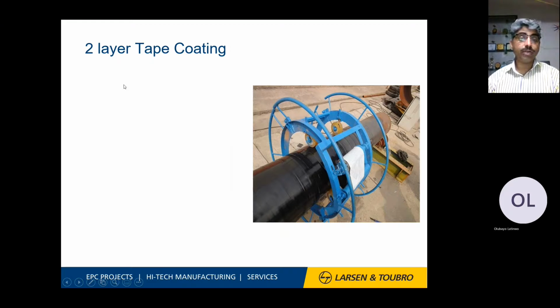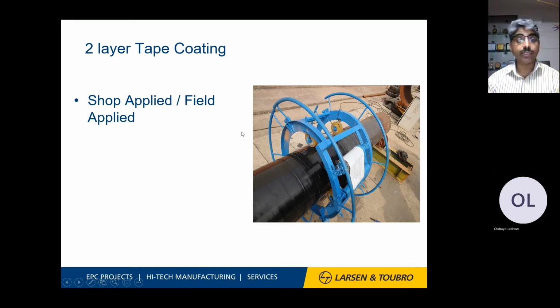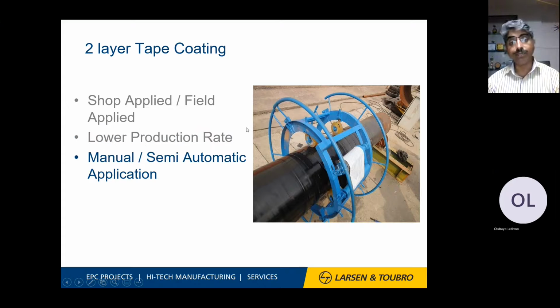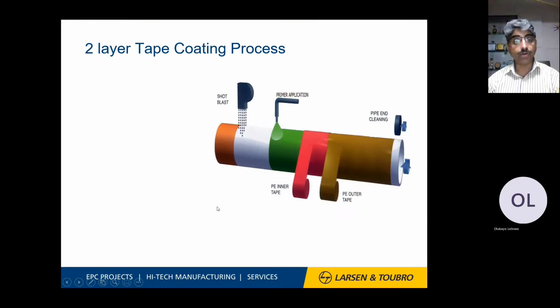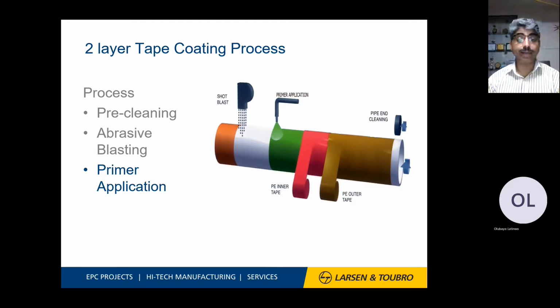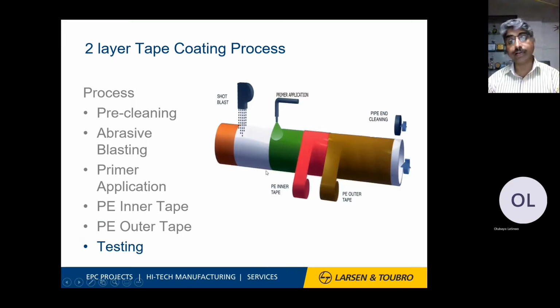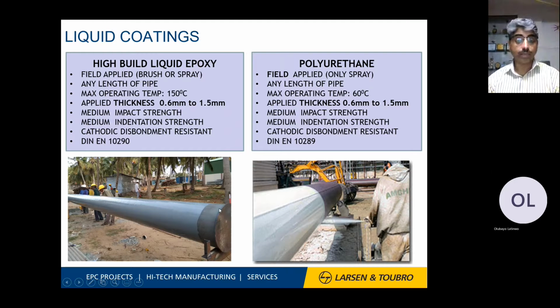The next coating for underground is the 2-layer tape coating. This is what the coating looks like. The machine or applicator applies it, moving over the direction of the coating, progressing from this side to this side. This is a shop and field applied coating. It has a low production rate because you have to apply it manually or do semi-automatic application. The process is pre-cleaning, abrasive blasting, primer application, and then PE inner tape coating and PE outer tape coating. Then comes testing for quality checks. This is how things are addressed in coating, in the field and at the shop.